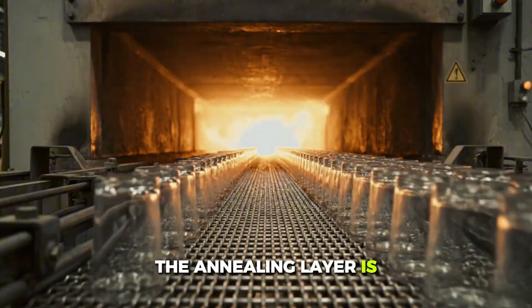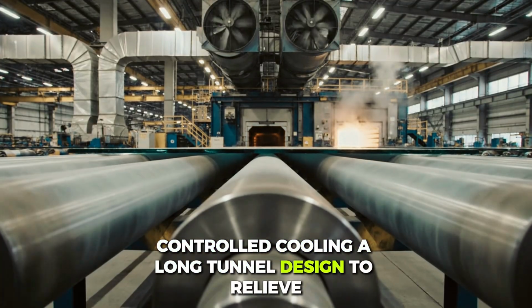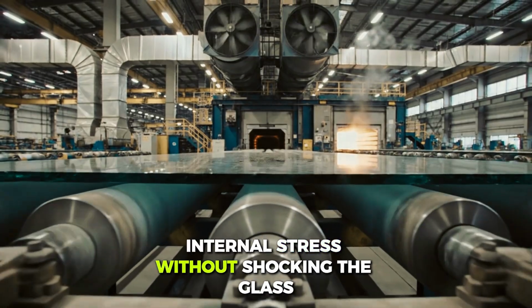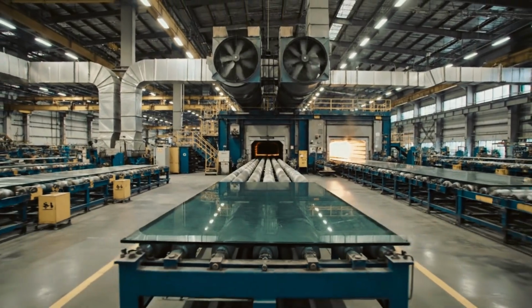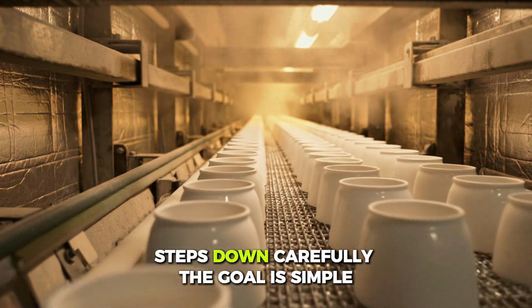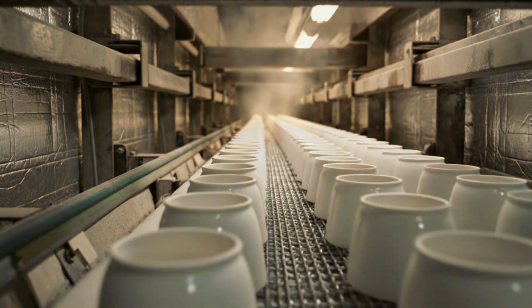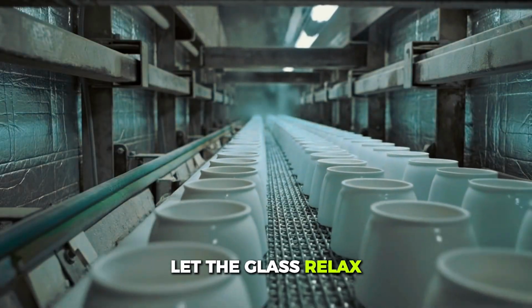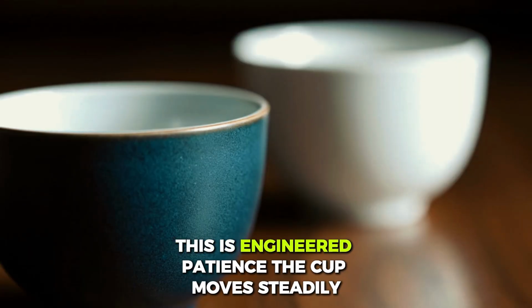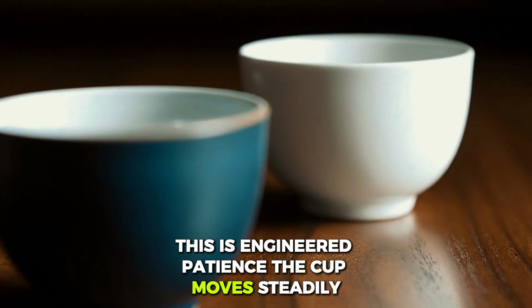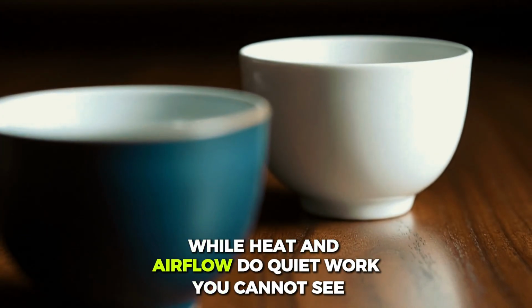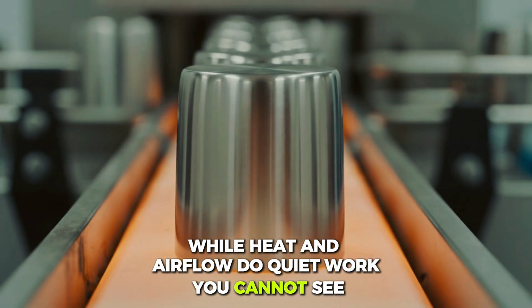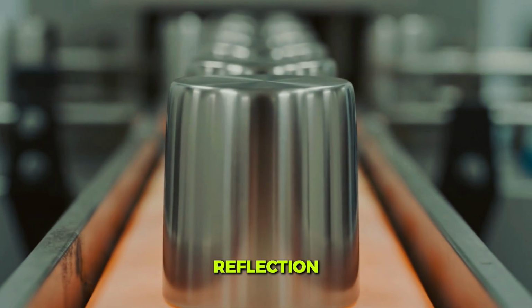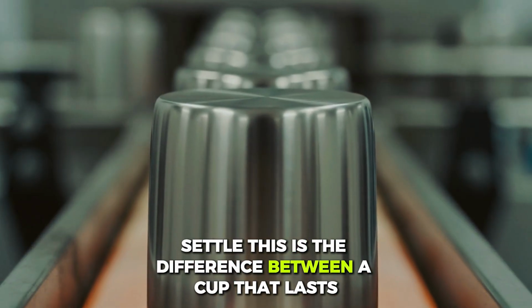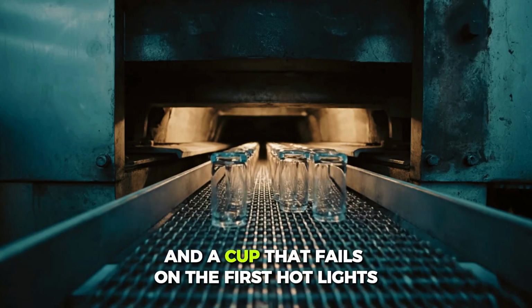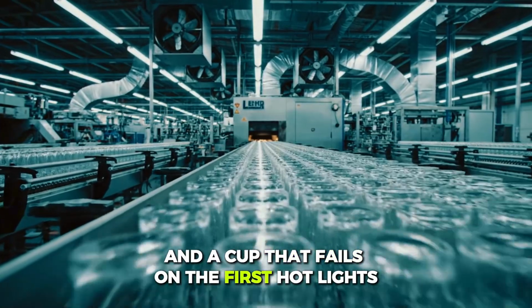The annealing lehr is controlled cooling, a long tunnel designed to relieve internal stress without shocking the glass. Temperature zones step down carefully. The goal is simple: let the glass relax. This is engineered patience. The cup moves steadily while heat and airflow do quiet work you cannot see. Stresses settle. This is the difference between a cup that lasts and a cup that fails on the first hot fill.